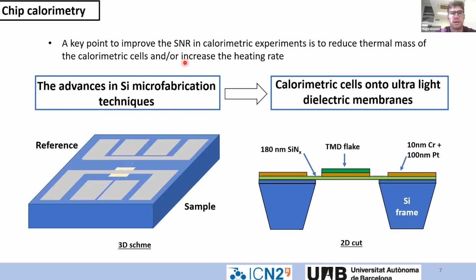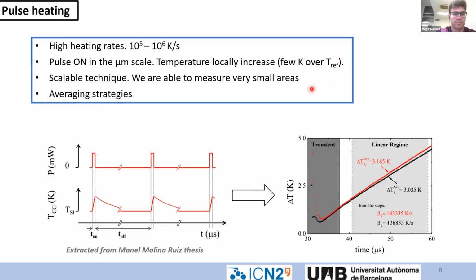The key point here is the signal to noise ratio, which is the sensitivity that we are going to have in this technique. It is improved when the heat capacity of the calorimetric cell is of the order of magnitude, at least, of our 2D material. So the advances in silicon microfabrication and the fact that we can have calorimetric cells with very light dielectric membranes make the heat capacity of these calorimetric cells even lower.